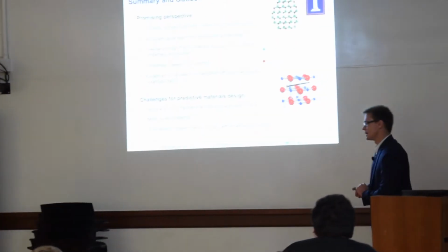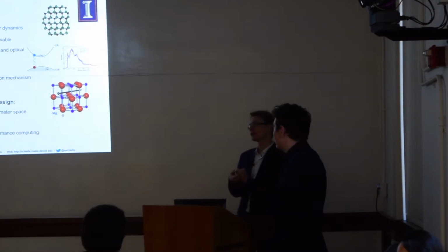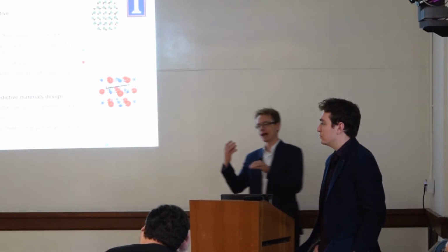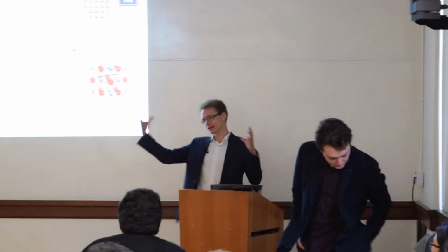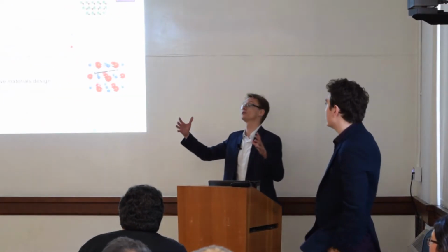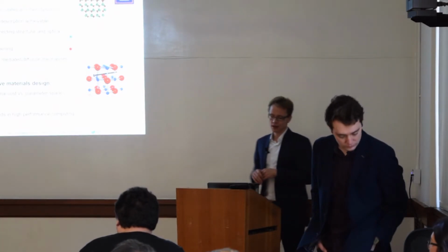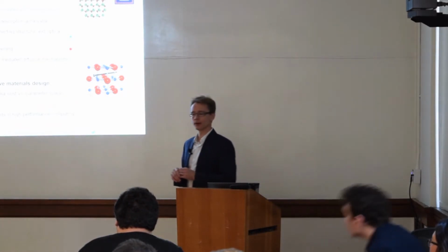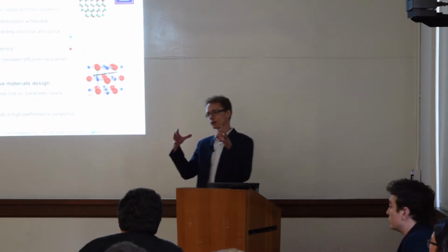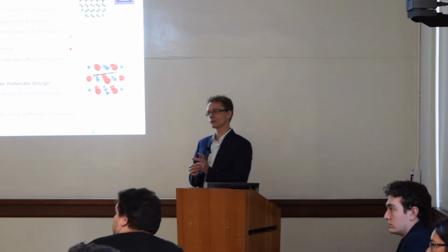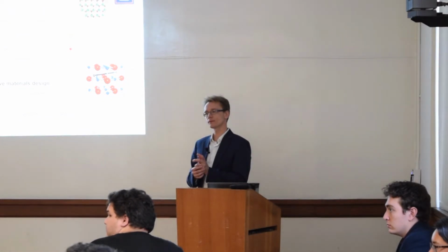Right. So, I guess the reason why I think the spectra are very similar is that the zinc blende and wurtzite structures are identical for first nearest neighbors, and only for larger nearest neighbor numbers start to deviate. So I think that can motivate why they're kind of similar. Now, why it doesn't change very much if you go from a bulk material to a surface or to a nanocrystal? For a nanocrystal, the presence of the surface is quite different for the wurtzite versus the zinc blende.